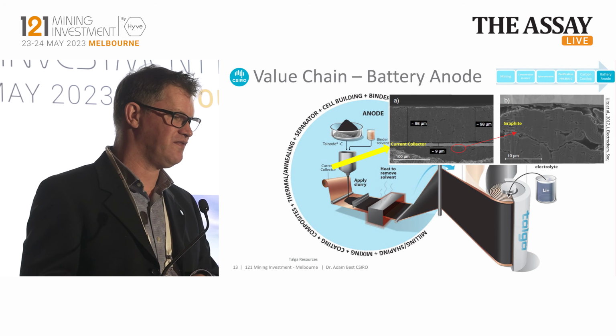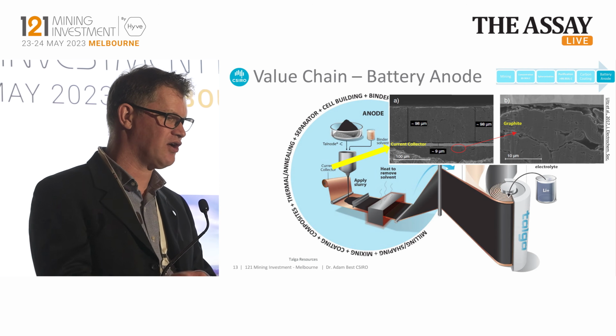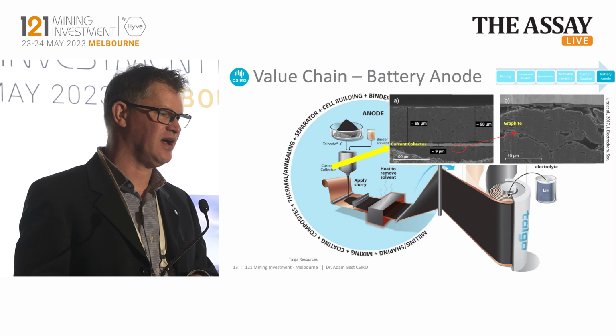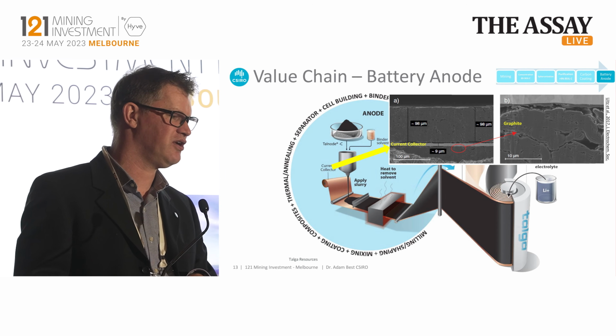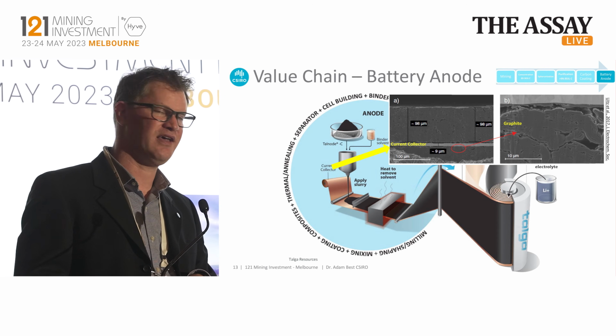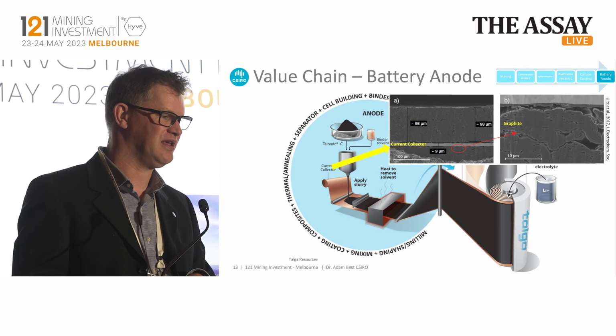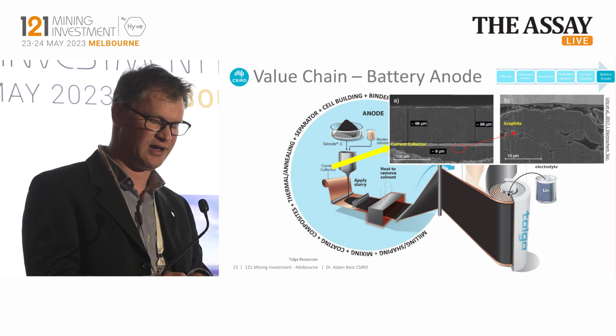And this is what it looks like when you finish. You can see here, this is a micrograph of the current collector and the graphite that's smudged into that electrode, depending on the size and thickness and the capacity that the company is looking for in its target energy density.